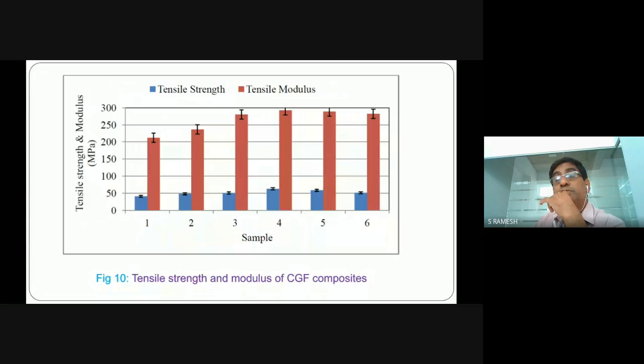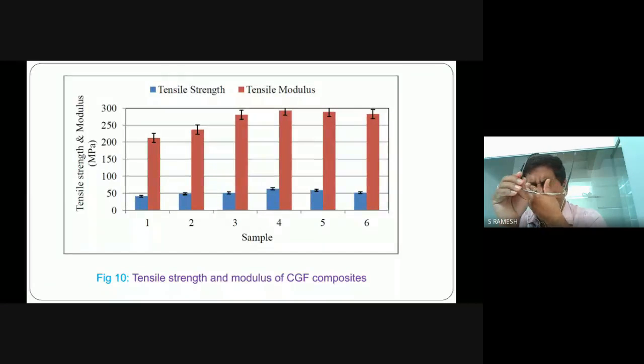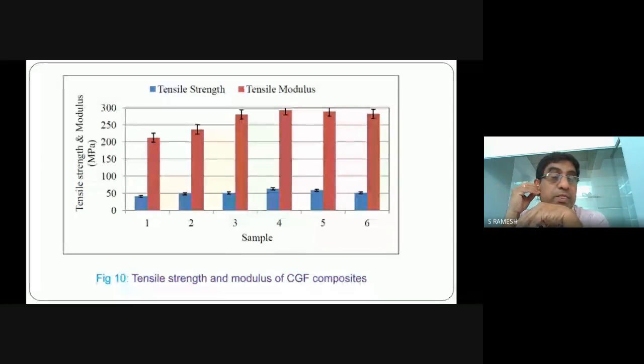In the analysis, we will eventually take nearly 6 samples. You can see that for tensile strength and modulus, the tensile strength varies from nearly 41 megapascal to 58 megapascal. If you observe the graph, we get 41 to 58 megapascal. Tensile strength means the maximum load that a material can support without fracture when being stretched, divided by the original cross-sectional area of the material.